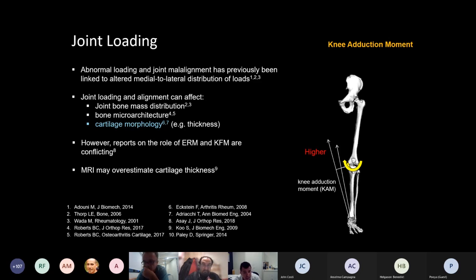But nobody really has taken these specimens and looked, with high-resolution imaging, at the cartilage and gait analysis on the same. Moreover, nobody really has combined bone, cartilage, and gait. Some studies have used MRI, but MRI, magnetic resonance imaging, has a spatial resolution of about 1 millimeter, and that's about the thickness of the cartilage. So the slice thickness corresponds to the thickness of the cartilage that we are measuring. So regions with thinner cartilage might not be captured.